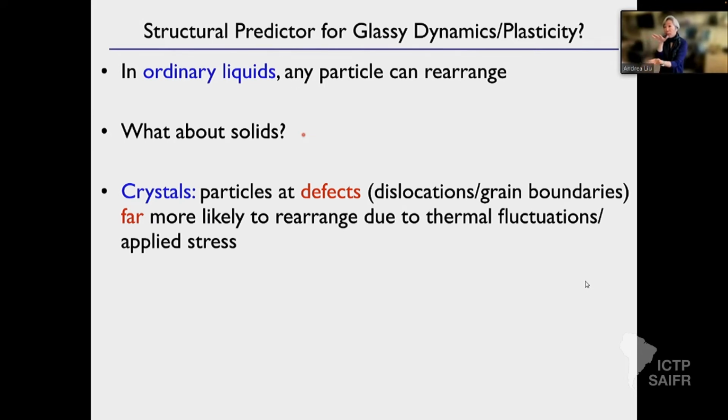What we're doing when we're straining things is we are deforming that landscape. We're lowering some barriers until they disappear and you can go over saddles, or they become lower and they form saddles. So what you're doing when you're straining the system is you're deforming that landscape and being dragged through it by deforming it. Okay. All right, so we agree it's a hard problem. Statistical physics has had a hard time with it in low dimensions.